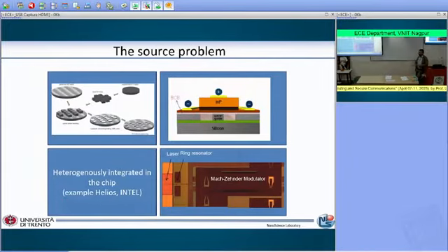And so the other option is to use what is called the heterogeneous integration of 3-5 on top of silicon. So you cannot grow 3-5 directly on silicon because of the lattice mismatch. Okay? This is the first problem. The second problem is the diffusion. The gallium and arsenic, the indium and phosphor diffuse into the silicon. You know that in silicon, phosphor is a dopant, but if you make an interface between indium phosphide and silicon at high temperature, the interface blurs. So you have a diffusion of phosphor from indium phosphide into silicon, which changes the properties of silicon as well as destroys your indium phosphide wafer. And so the direct heteroepitaxy of 3-5 on top of silicon is not possible.